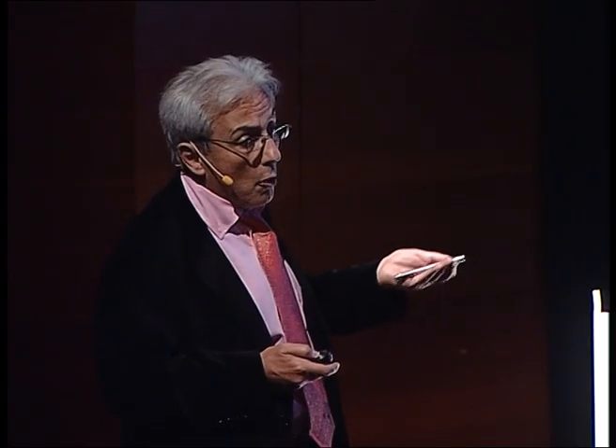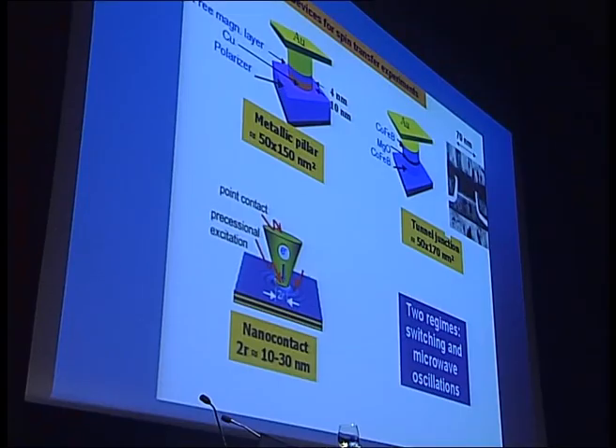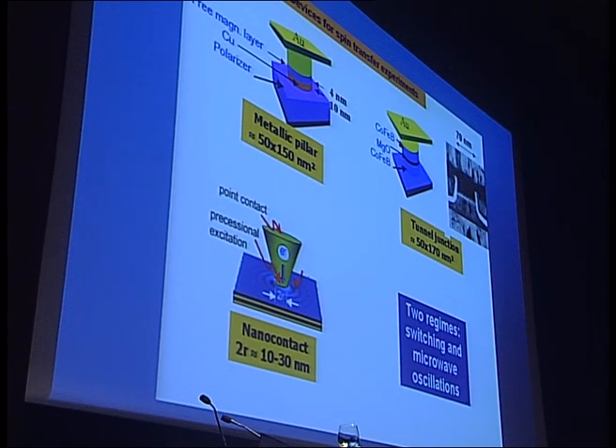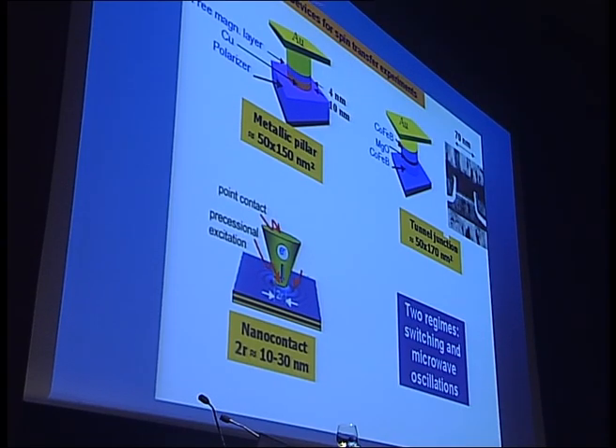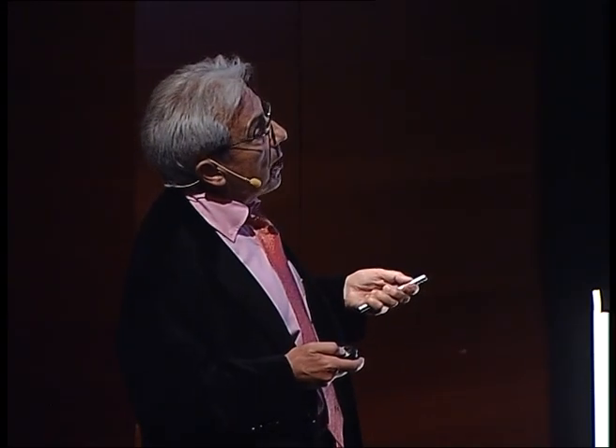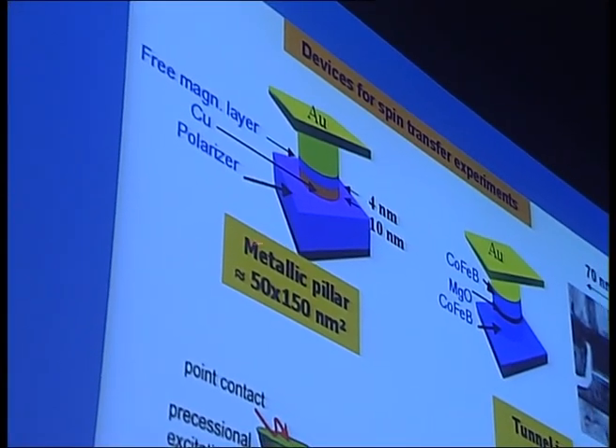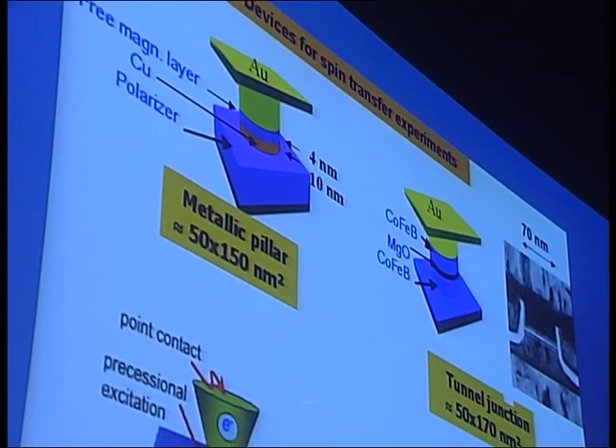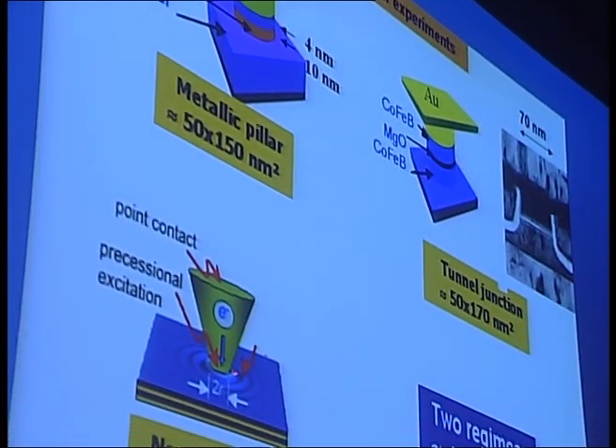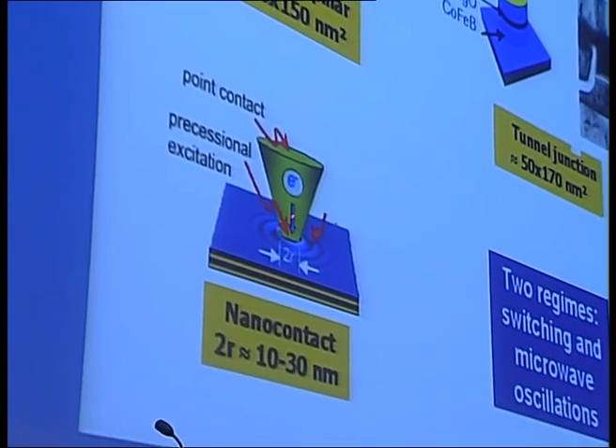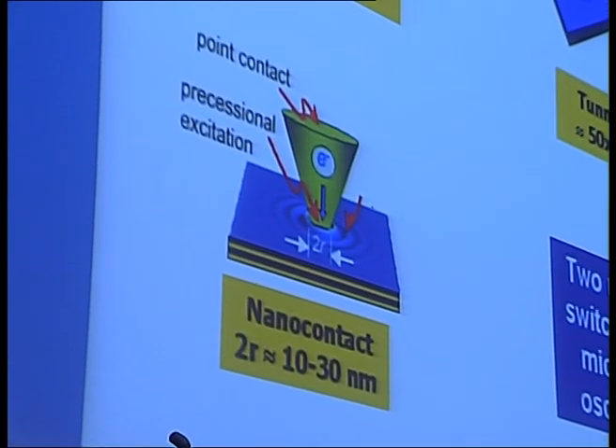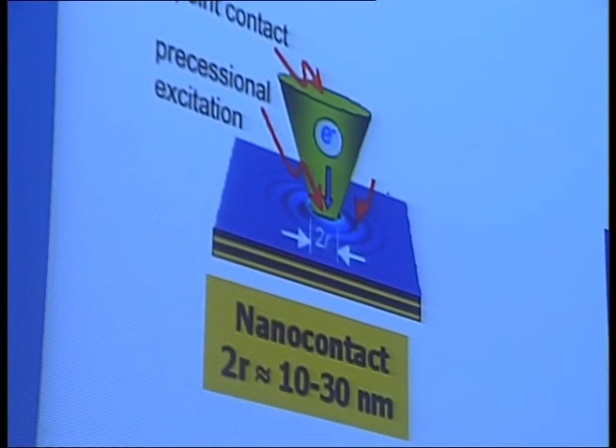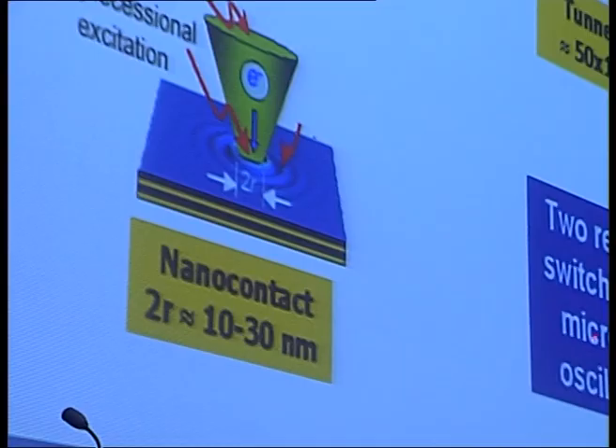And so this spin transfer torque can be used for different manipulation of the magnetization of layers or small objects. In general, because one needs a relatively large current density to move the magnetization of a magnetic layer, the current has been confined in a small section to obtain this high density. For example, in this structure, metallic pillar tunnel junctions prepared by e-beam lithography. You can see the size of the pillar is of the order of 100 nanometers, or simply also by injecting through a small nanocontact into a trilayer to confine the current in a small area. And I will describe the two regimes, switching of the magnetization by spin transfer at low field, or generation of microwaves at larger field in general.